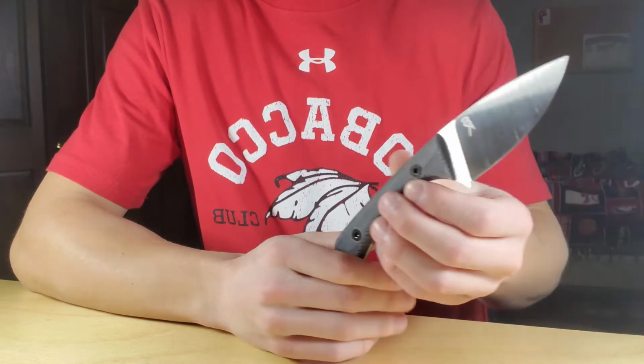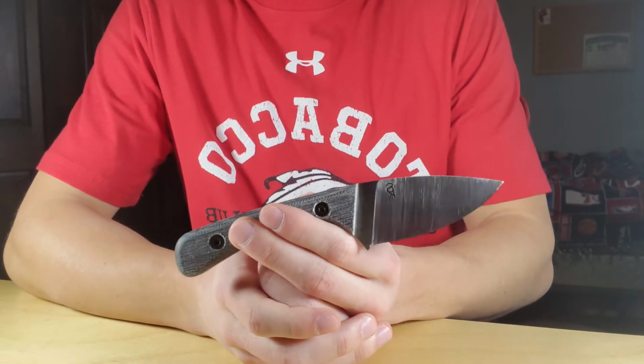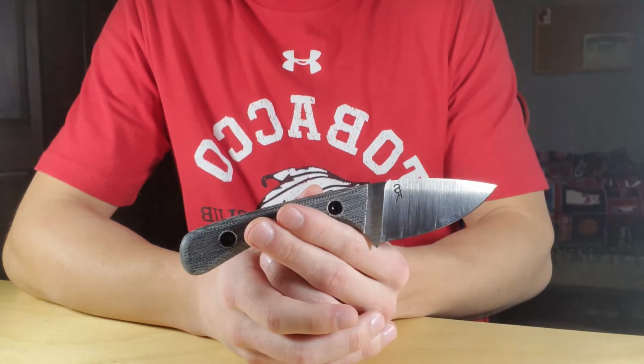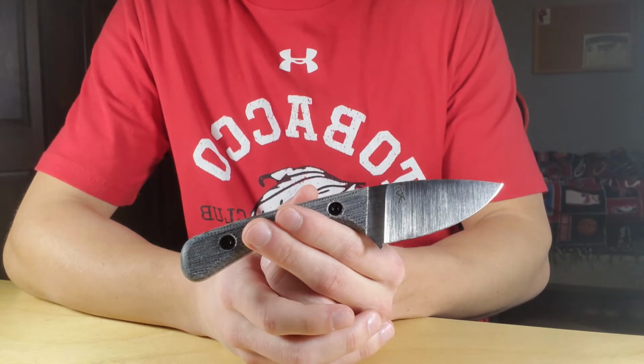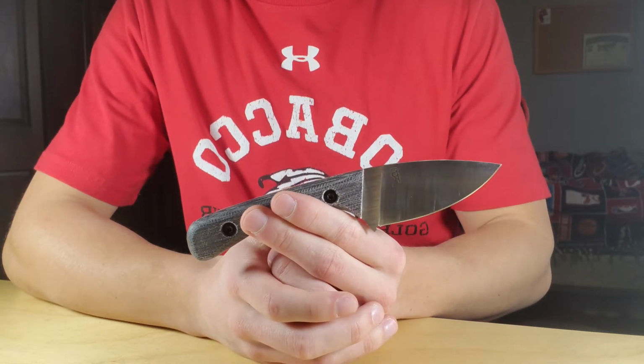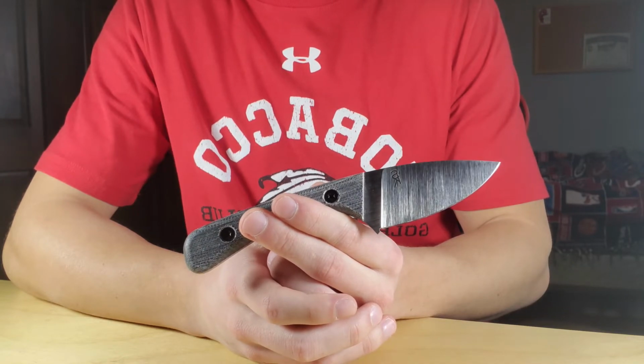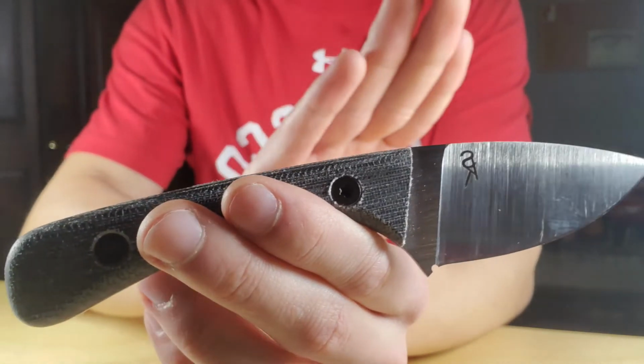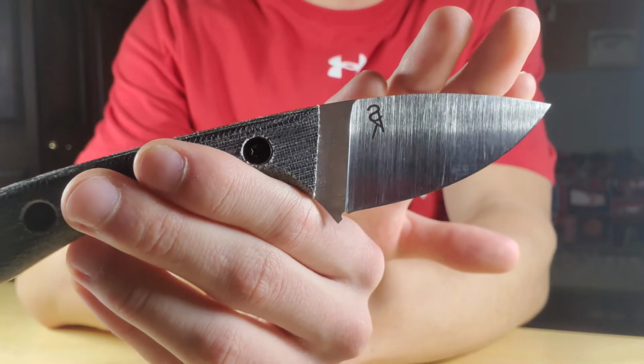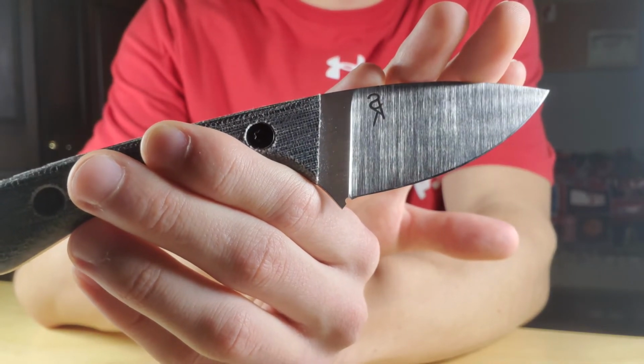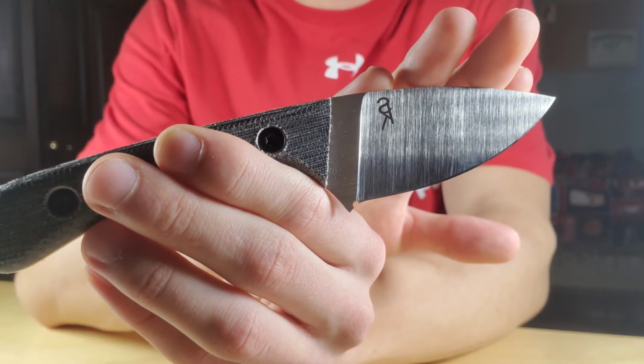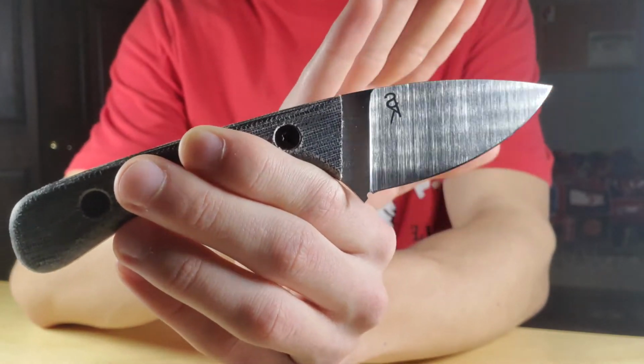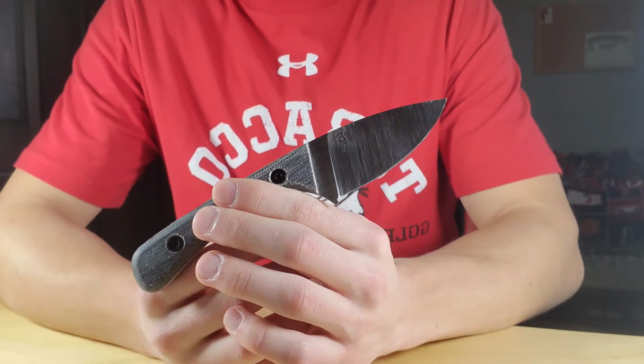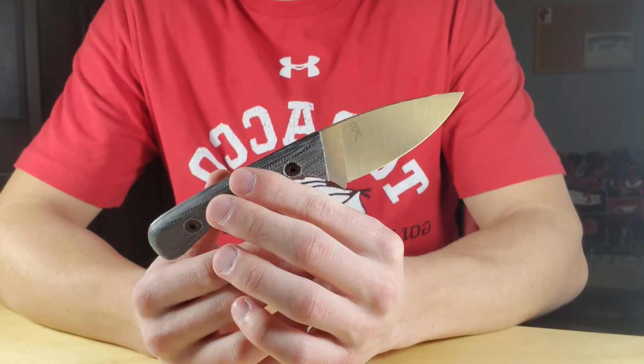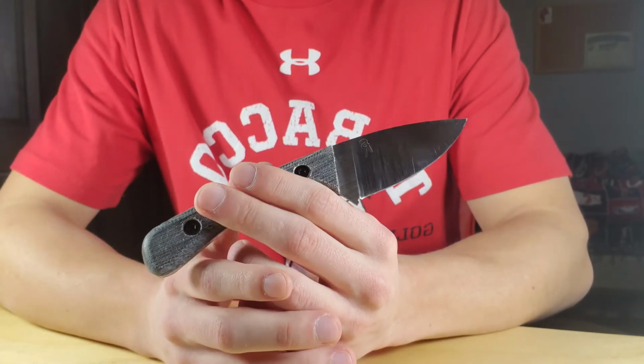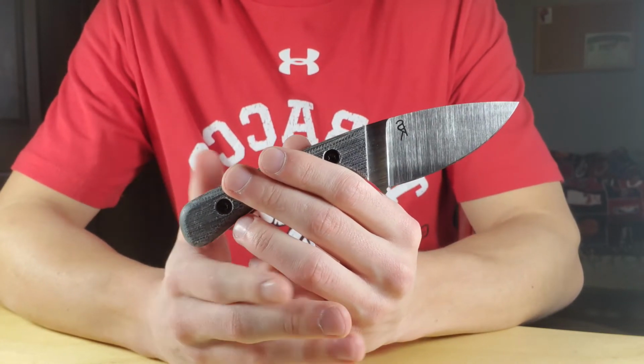I took this Steingraber Performance Knives Shark in K390, and this was one of his initial ones. He's done quite a few runs since then. But this one is sitting at 65.9 HRC, and it's sharpened at 13 degrees per side. I'm not sure how easy it's going to be to see how small that bevel is at 13 degrees per side, but I sharpened it with a full diamond progression, and it's sitting at 12 thousandths behind the edge right now. Absolute laser beam.